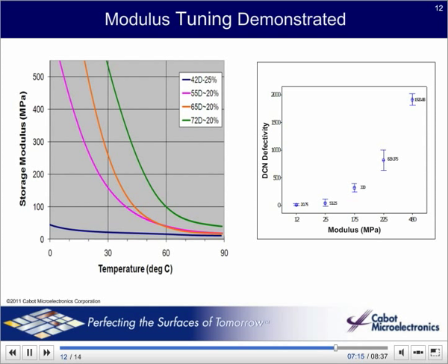For buffing processes where extremely good final surfaces and low scratch are critical, but removal rate is not too high, then the soft 42 durometer rubber works well. For higher removal rates, for example during the first step bulk removal of copper or oxide, a harder pad is usually best.